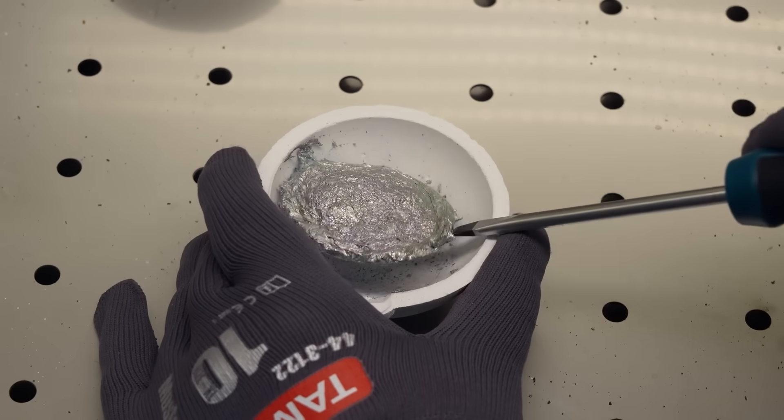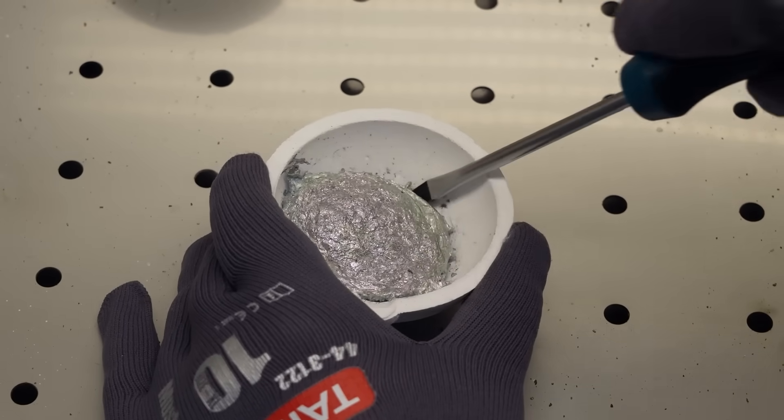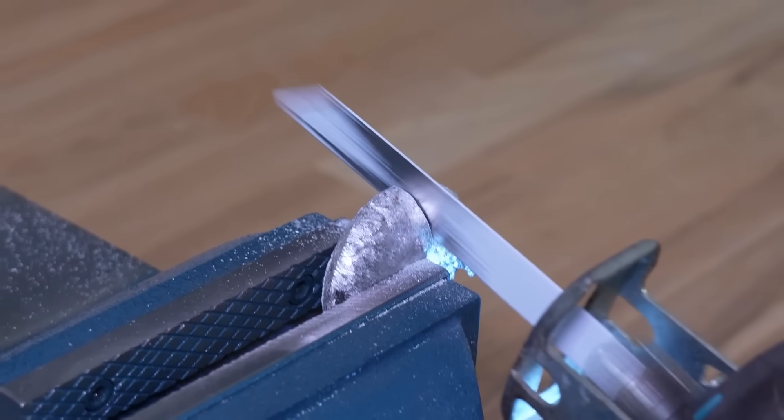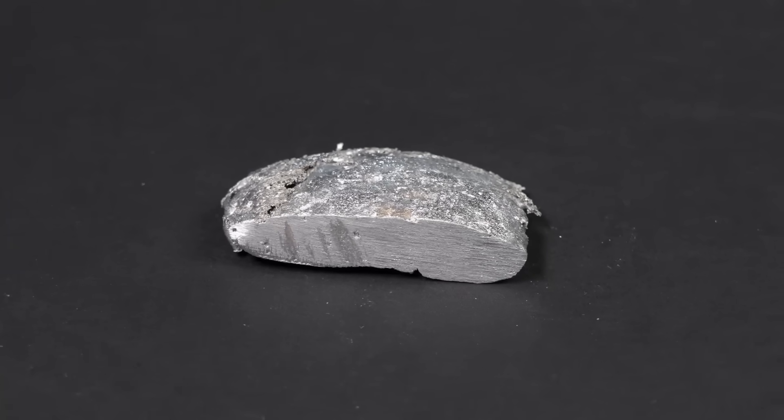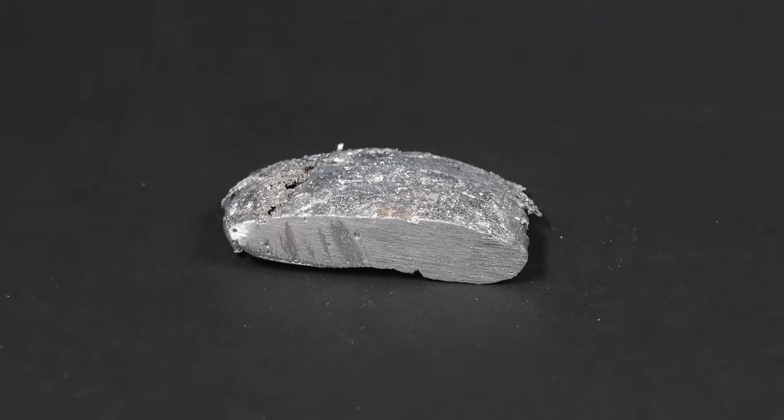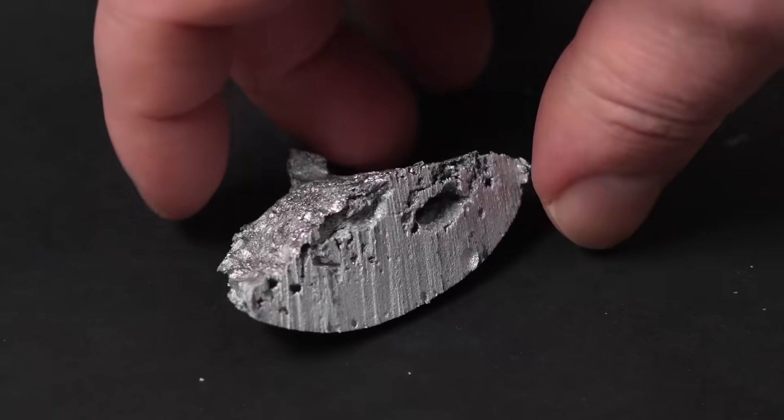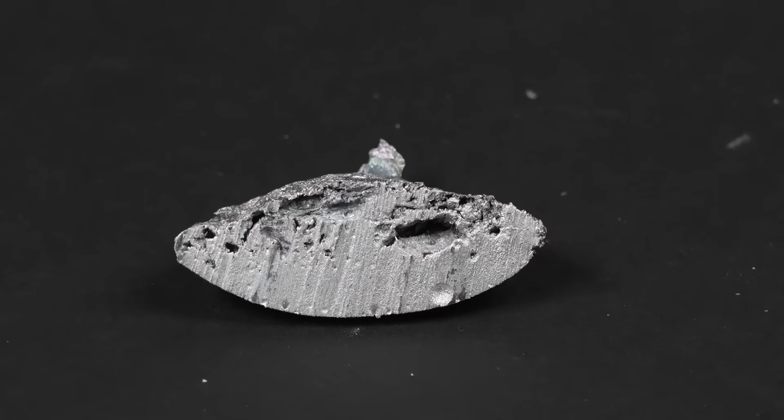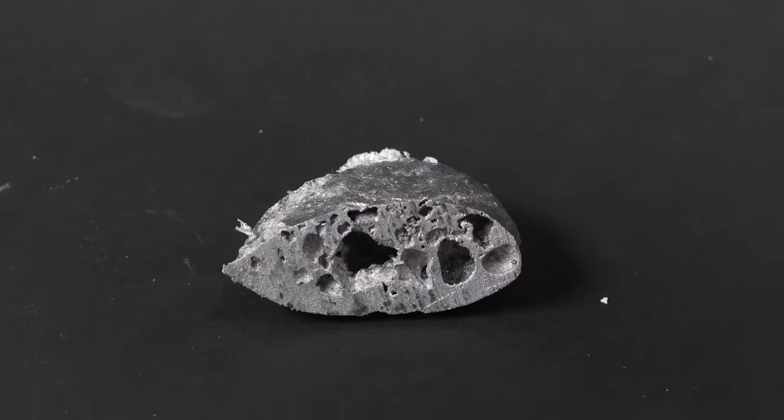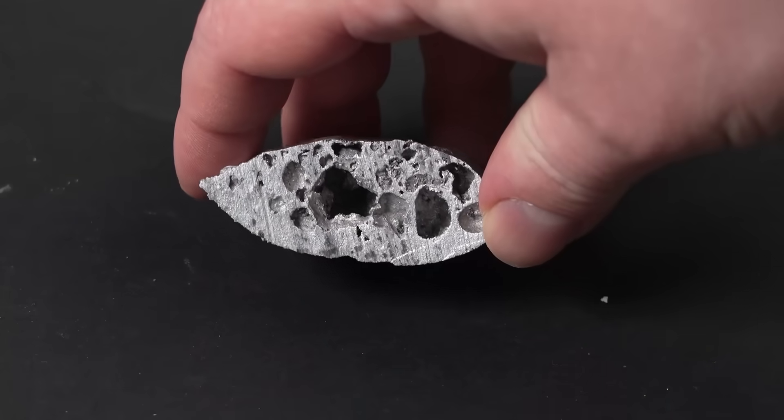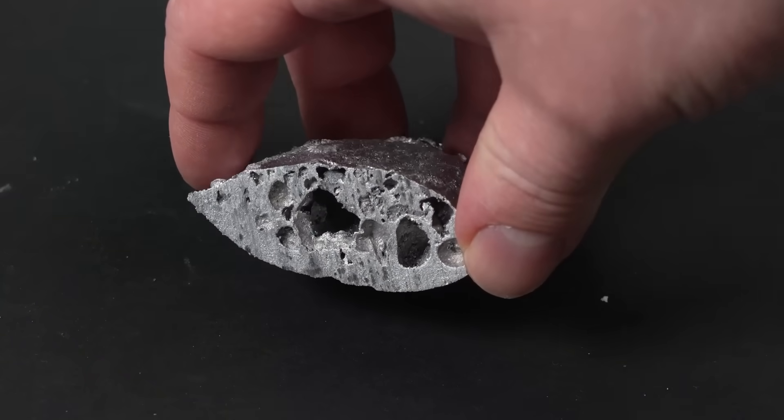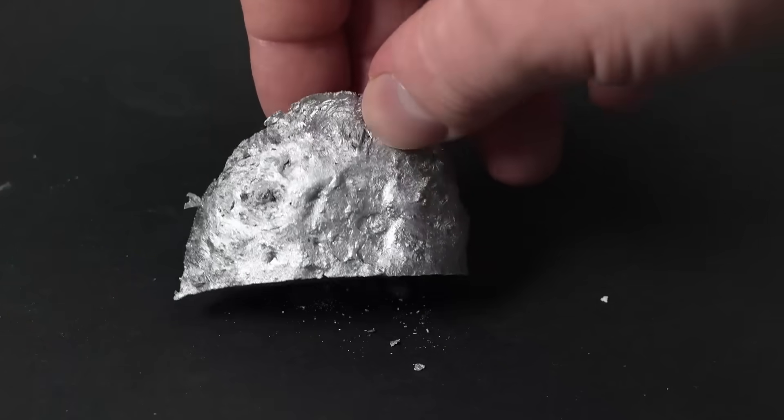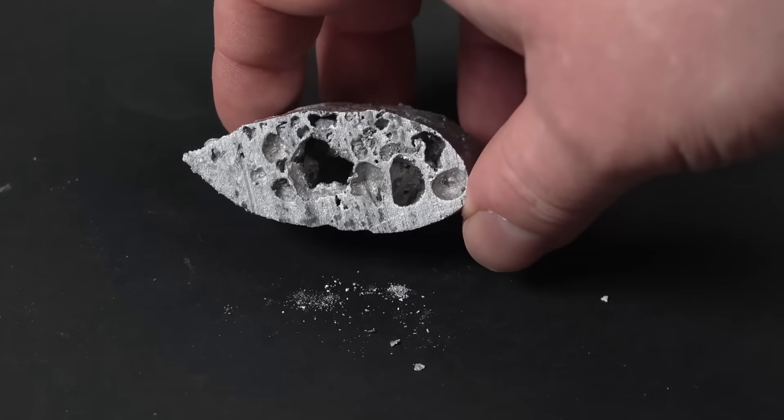Maybe we need to heat the alloy a bit more so that it can dissolve more hydrogen. And yes, you heard that right. At high temperatures, in some metals, particularly aluminum, a small amount of hydrogen can dissolve. And if you don't degass such an alloy or metal, then during solidification, it may form shells or bubbles that resemble that very metallic foam. However, after heating and cooling, the foam didn't really turn out well the first time.